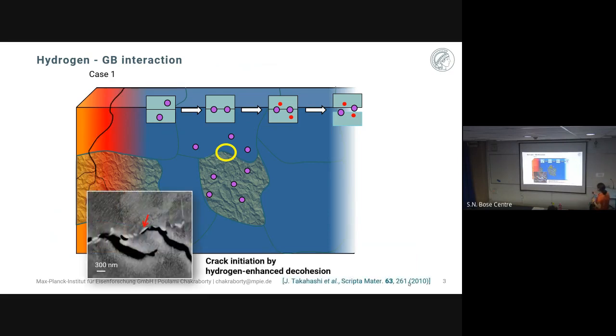Having said this, as you can see, this is an experimental picture taken from this reference, where they show that the crack is initiated by hydrogen enhanced decohesion, that is the HEDE mechanism we were talking about before. Here there is a crack formation, and they have seen that after electrochemically charging the material over a long time, this crack is being formed.